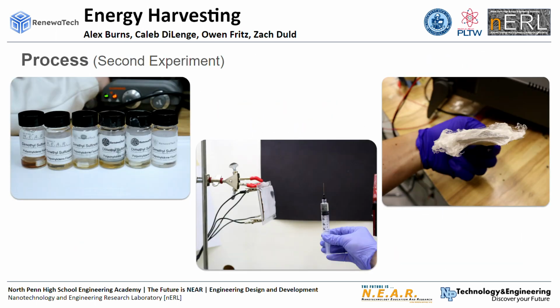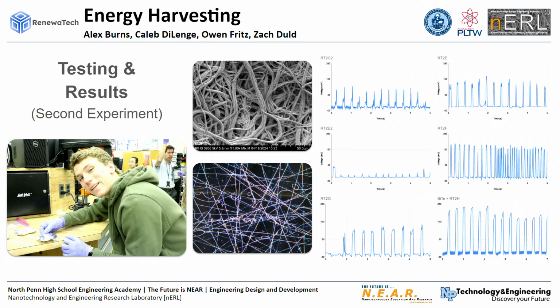For our piezoelectric material, we used PVDF, or polyvinylidene fluoride. We used it due to its large amount of pre-existing research, ease of use, and relative efficiency for what we wanted. To test our PVDF, we used a similar but slightly different method. We utilized an Analog Discovery 2 device to record the voltage over time. Alex periodically tapped our material, and we recorded an average peak voltage of 200 millivolts on our best trial.